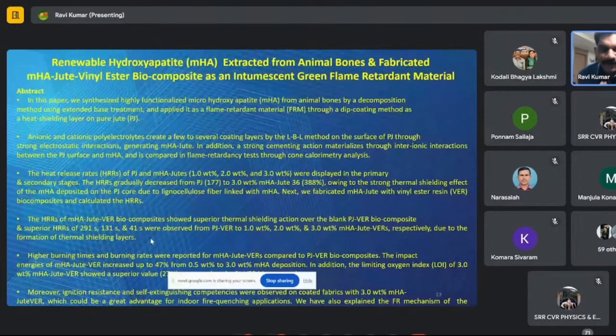So these panels are very important, and we used the heat release rates. Also, we tested on pure jute and MHA jutes at 1 weight percent, 2 weight percent, and 3 weight percent. We stopped at 3 weight percent because if we increase further, the brittleness of the material will increase. And the secondary stages we also studied here.